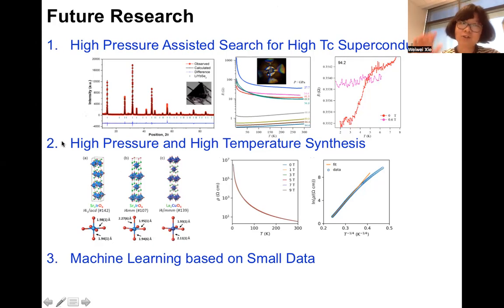The second direction is using high temperature and high pressure methods together to synthesize new materials, which could potentially be high Tc superconductors, as well as to understand high Tc superconductors. For example, Sr2IrO4 is a material people say is the sister material of the high Tc superconductor La2CuO4. We pressed this one under high pressure and high temperature, and found a new phase of Sr2IrO4 that is non-centrosymmetric. This material is more similar to La2CuO4 than the ambient pressure phase. We are studying it and trying to understand what exactly is going on in high temperature superconductors.